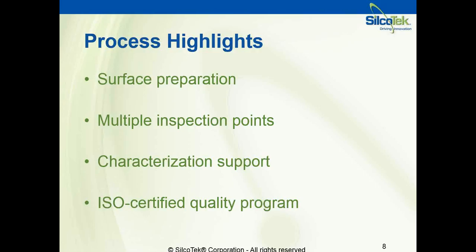So in addition to the actual deposition of the coating here at SilcoTek, we do offer various steps that are designed to meet the needs of specific applications. So surface preparation, we do a custom surface preparation based on the metallurgy of the base substrate that we'll be coating. And this is extremely important to a high quality deposition later on. Even fingerprints and greases will highlight other defects in both the coating and the substrate. So it's extremely important to have a very clean, bare, stainless, or whatever the material may be, surface going into the CVD process.